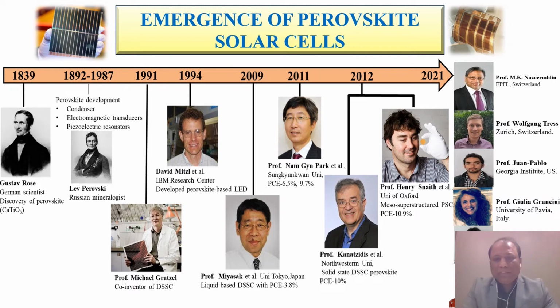In 2011, Professor Park used the same material and structure, but a more concentrated perovskite material, and he got 6.5% in 2011. But he had a problem. He was using an electrolyte, and the perovskite material got dissolved in the electrolyte and vanished. So he was thinking of using something else instead. Then he got an idea, an old idea actually, which Grätzel had used. Grätzel was trying some organic materials before, Spiro. Instead of the electrolyte, Park used Spiro. This organic material helped him reach an efficiency of 9.7%. Then everything started.